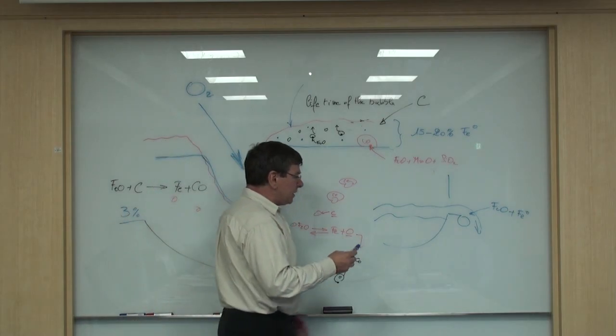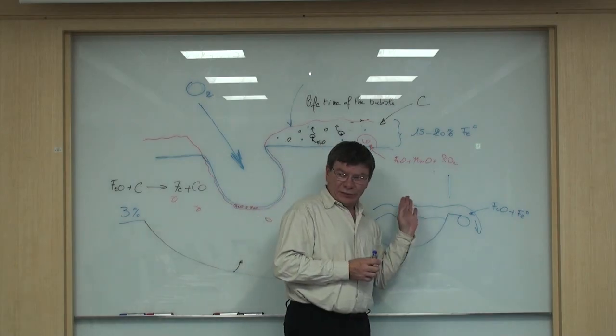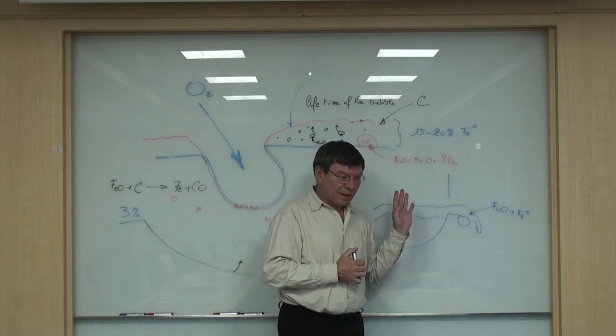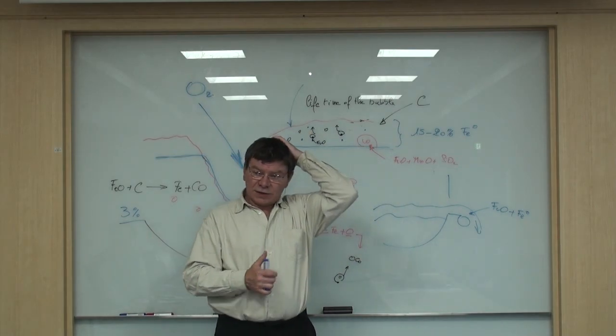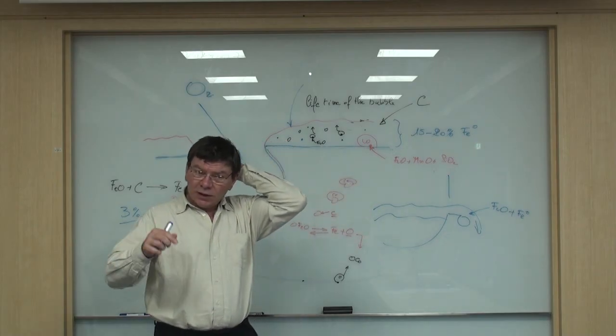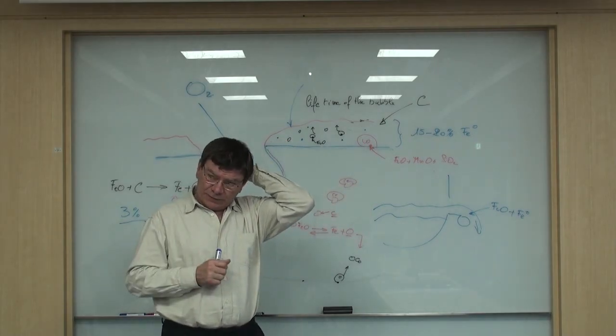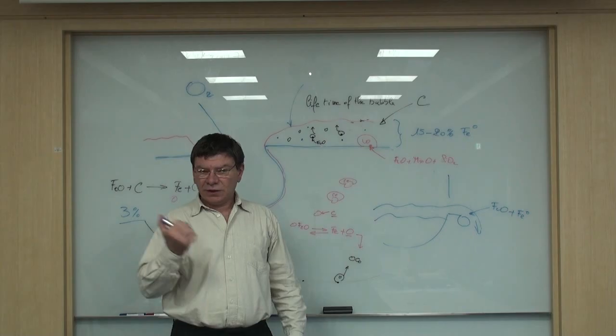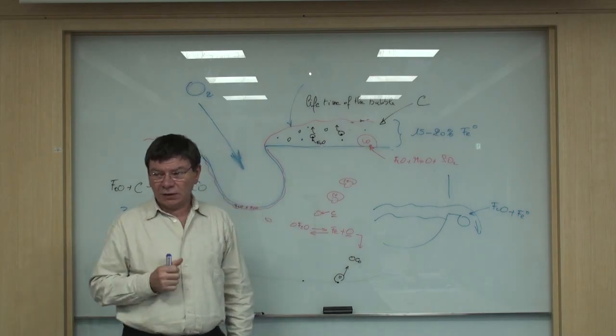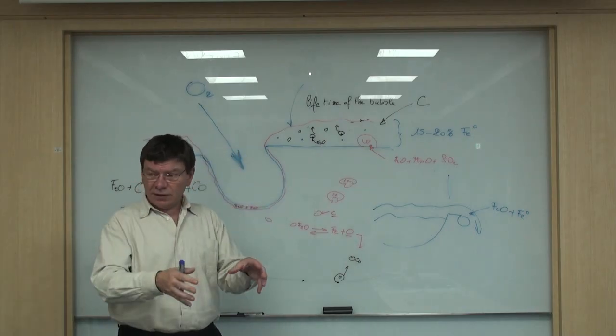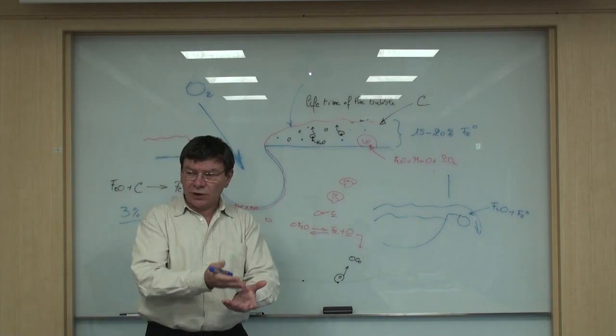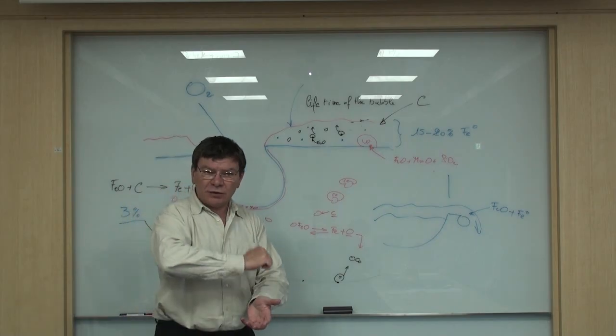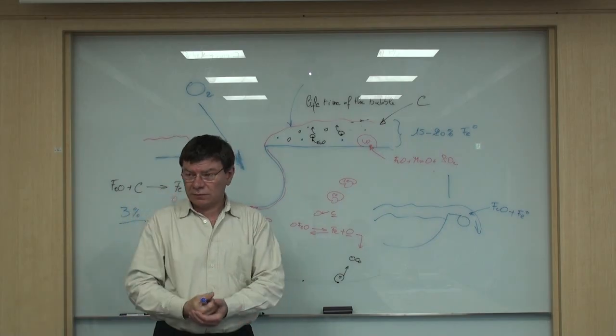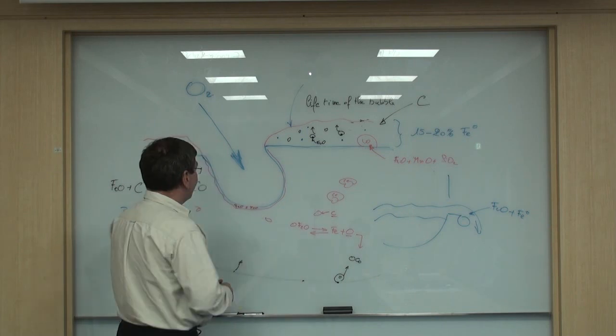Then what I say is that taking the last sample is a lie. Because in a conventional furnace, especially nowadays with the supersonic injectors, people start oxygen injection from the beginning. You still have scrap in the furnace, you don't have access to the liquid pool, but they inject a lot of oxygen, so they burn iron.